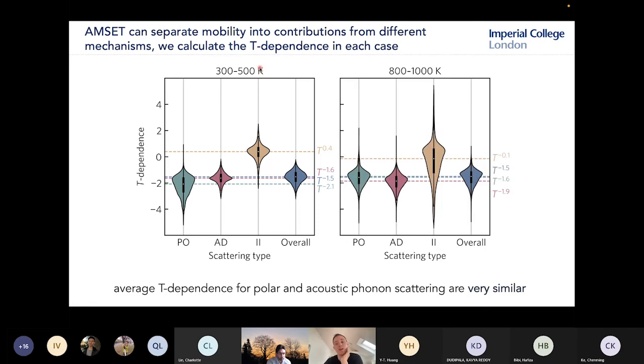This is at low temperature. At high temperature, it just gets even worse. These distributions overlap even more, and the average values for the temperature dependence of the entire data set get even closer. So really, this is exactly confirming what we saw in the DFPT plus Wannier data set, which is that it's basically impossible to determine the dominant scattering mechanism based only on the temperature dependence of mobility. You really need to take into account other things if you're going to determine what is dominating in your material.